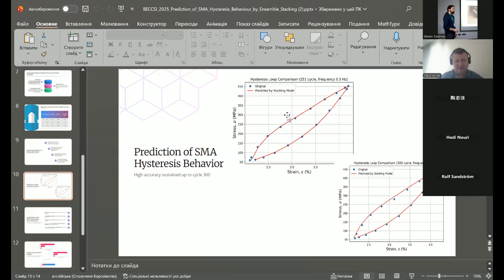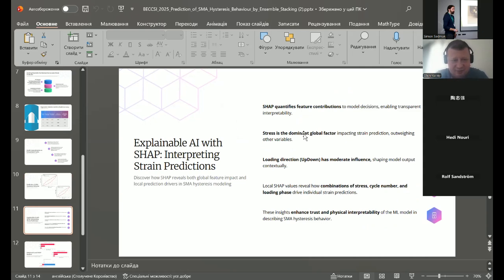On this graph, you can see hysteresis loop comparison for the 251 cycle at frequency 0.3 Hz. As you see, the results are quite good. And here you can see the prediction of the hysteresis loop for cycle number 300. The results are quite good, though the model has seen the cycles only up to 250, but it's acceptable, I suppose. We have also employed explainable AI with SHAP, interpreting strain prediction.